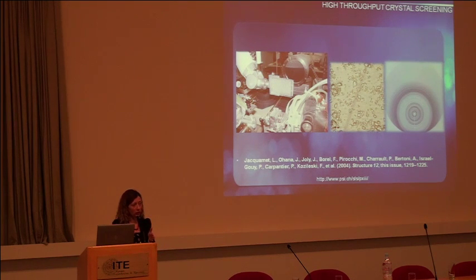successful crystallization conditions. So one suggestion for you is to use the method simply for screening your crystallization screens. That's the easiest. If you see rings, like these ones, you have something crystalline. The next level is to separate salt from protein crystals. Salt crystals appear in completely different 2 theta ranges, and therefore by simply collecting this data, you know if you managed to crystallize your protein or if it's another of the crystallization agents you used.